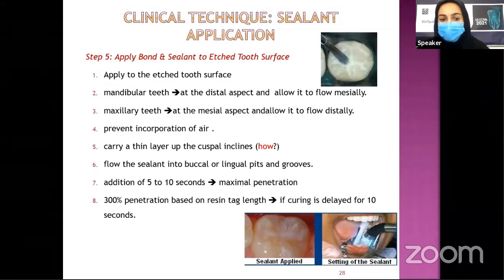Carry a thin layer onto the cuspal inclines, again using a micro brush or a burnisher. Then flow the sealant into the buccal and lingual pits and grooves, which are caries susceptible. An additional time of 5 to 10 seconds helps you get maximal penetration of the sealants and bonding agents into the etching tags. And if the curing is delayed for 10 seconds, you have 300% penetration based on the resin tag length.